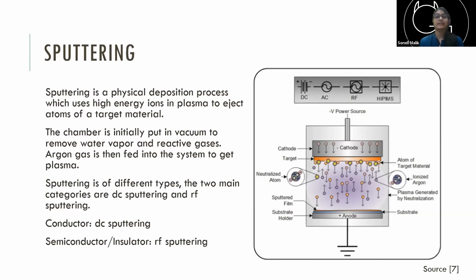Sputtering is essentially mainly, there are also other types, but there is DC sputtering and RF sputtering. DC sputtering is used for conductors, and in this case you just have a DC bias across your cathode and anode. For semiconductors and insulators, because high energy argon ions go and strike your target, if your target is not a conductor, it will continue to accumulate positive charge, right? Unless it can discharge all of that into the rest of the circuit.